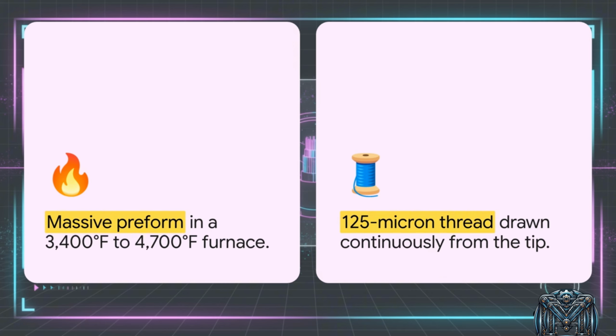Just think about the extremes here. We feed this massive 25mm preform into a furnace blazing anywhere from 3400 to 4700 degrees Fahrenheit. The glass softens just enough, kind of to the consistency of warm caramel, and gravity takes over, pulling a continuous, incredibly delicate 125 micron flexible glass thread down from the tip. That single massive rod can be elongated into up to 40 kilometers of continuous fiber.